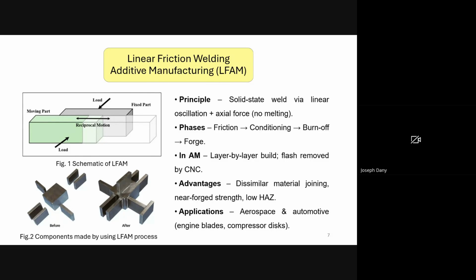Next comes the third phase, known as the burn-off or equilibrium phase. Here, the axial forces increase, causing plastic flow of the softened material, which is extruded outward as flash. This results in a reduction of the axial length of the weld assembly, and it ensures thorough bonding across the interface. The final phase is the forge or consolidation stage, where the oscillating motion ceases and the parts are held together under sustained pressure to cool and solidify the bond. During this stage, residual stresses develop as the material consolidates, but the solid state process helps keep these stresses lower than what occurs in fusion welding.